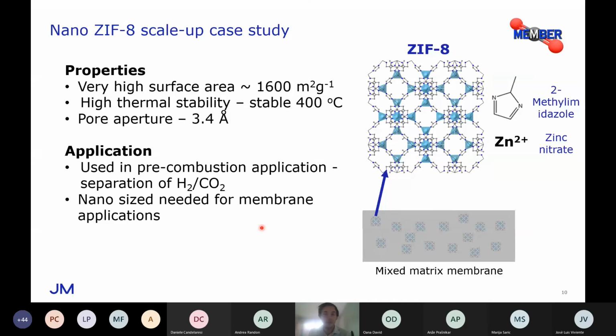Okay, so now I'll just go through a MOF scale-up case study. This work was done as part of the MEMBER project, in which we look to try and scale up nano-ZIF-8. ZIF-8 is the structure on the side here, and it's made from an organic linker called 2-methylimidazole and zinc ions. In this case, we use zinc nitrate as a source of zinc ions. It produces a very porous material with a high surface area, and it's also quite stable, stable up to 400 degrees Celsius.